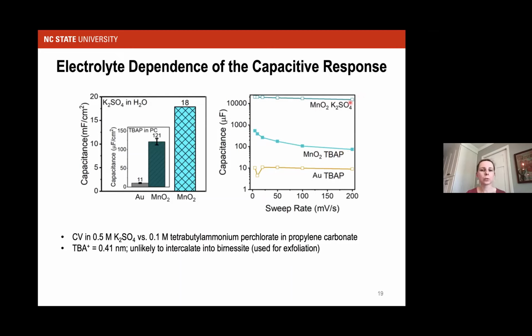So since tetrabutyl ammonium is about 0.41 nanometers in size, it's unlikely to intercalate. So it really is telling us what's the outer surface contribution to the process. And so since we see this very significant distinction, we think that our electrochemical response is due to either cation insertion or potentially the role of protons.